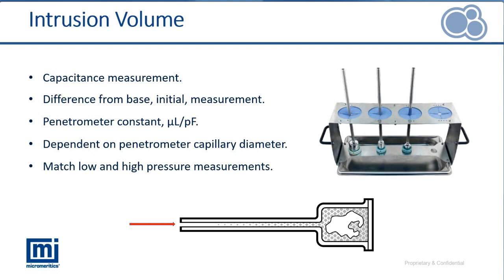Now, I showed you that the instrument consists of both a lower pressure portion on the top and a high pressure portion in the bottom. We do match together those data that are collected by those so that we get a smooth transition between the low and the high pressure. And if you recall, I showed you that the penetrometers have different diameters for that capillary region. Each one of those capillary diameters has a slightly different penetrometer constant. And we simply just enter that when we're setting up the software analysis.